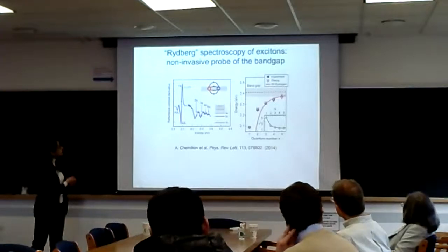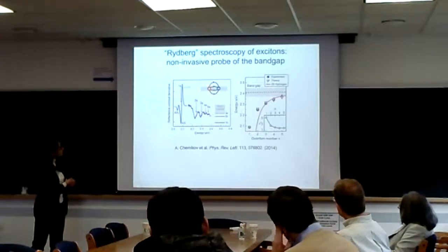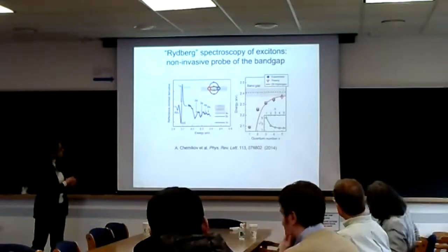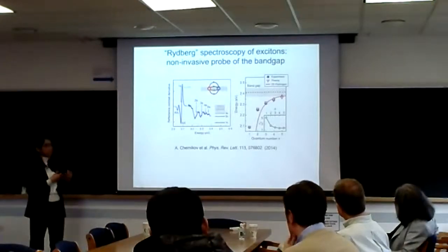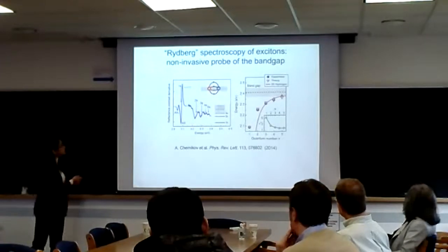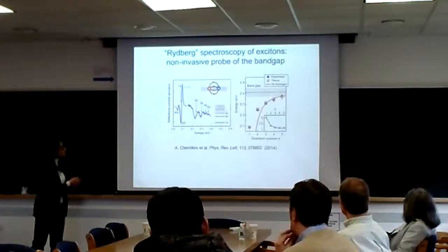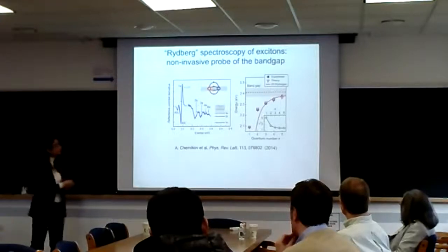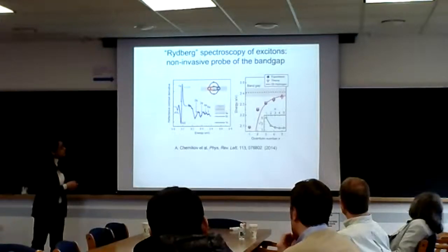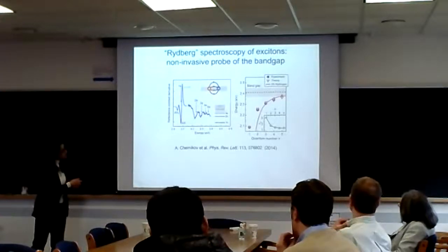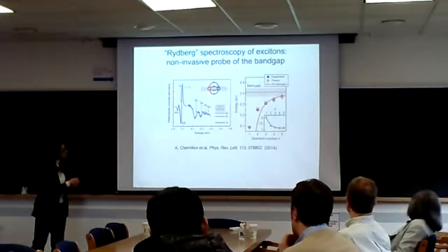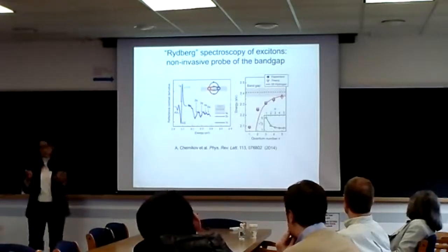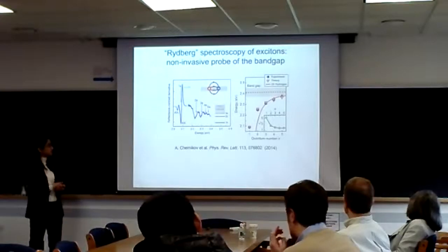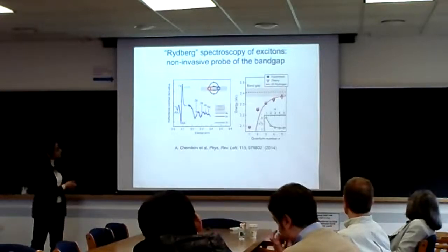So what was done in this paper is that you can observe the ground state and the excited states of the exciton, just like the way you think of the hydrogen atom, 1s, 2s, and so on. And experimentally, this should converge towards the quasi-particle edge. By looking at the states converging, you can read out this number of 300 meV, and that's the binding energy in the system.